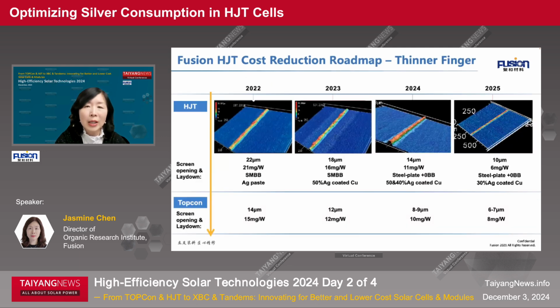This slide shows the cost reduction roadmap for thinner fingers. From 2022 to 2024, the HJT silver consumption is still higher than TOPCon. The screen opening goes from 22 micrometers in 2022 to 14 micrometers in 2024. The silver consumption is reduced from 21 to 11 milligrams per watt, still a little higher than TOPCon.